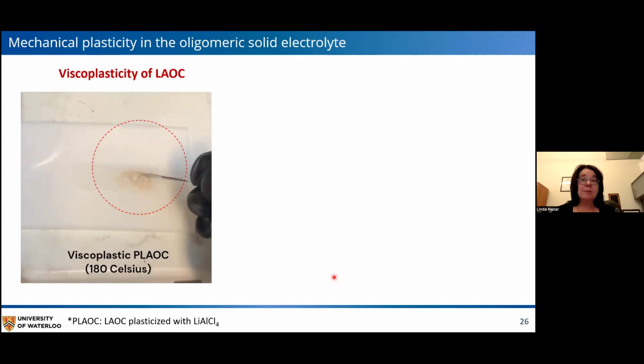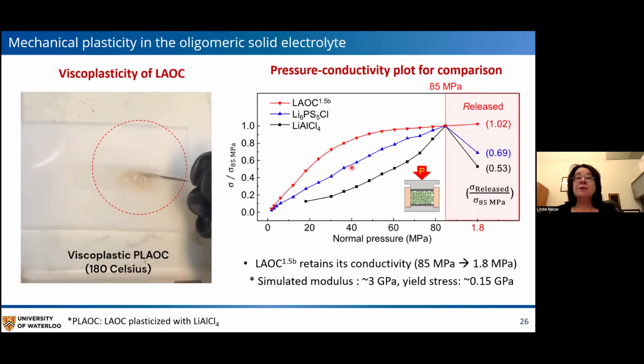And I'll just move over here. This compares the conductivity with pressure for lithium aluminum chloride, the argyrodite, for example, and our LAOC. And when we release the pressure, the conductivity for LAOC remains the same, whereas, of course, it drops for argyrodite and for lithium aluminum chloride. And we can simulate a modulus, which is on the order of 3 gigapascals with a yield strength of about 0.15. And I'll get to the mechanical properties in a moment, because I'm almost running out of time, but I have just a few more slides.